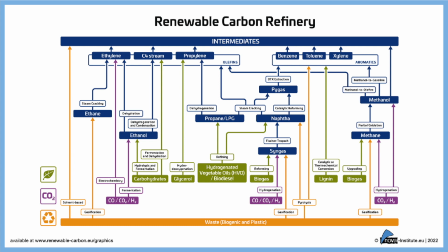We also have a lot of waste from the different bio-based industries, for example the paper and pulp industries producing lignin, and lignin can be further carbonized to produce the carbon I was mentioning earlier, which could be used directly as an additive or functional additive, but lignin can also be used as a base chemical for making new polymers.